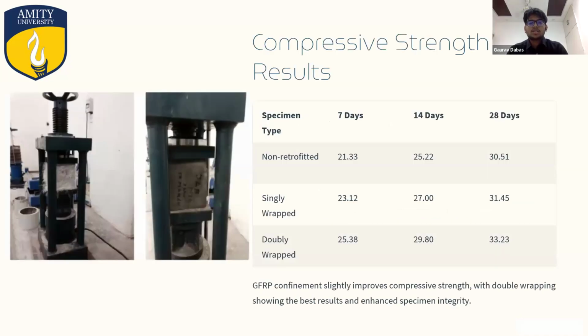Now, following our compressive strength results, as you can see, compressive strength improved slightly with GFRP wrapping. Doubly wrapped specimens reached 33.23 MPa after 28 days. Although not a dramatic change, these improvements indicate that GFRP helps maintain concrete integrity under stress. It provides support but does not completely replace reinforcement.